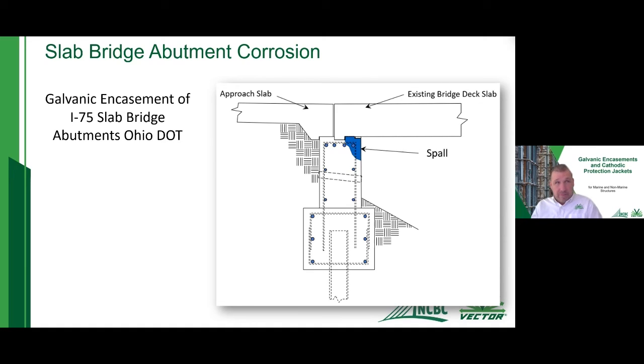So it's going to use very, very similar anodes that were used in these jacket encasements or these CP jackets. So you can think of this as just a very, very large atmospheric jacket that's going to be used in an area where it's a non-marine environment. So this is actually an abutment for the Ohio DOT. And so traditionally what they would do is they get some spalling that would happen up here. So you have your approach slab, you have your existing bridge deck, you have an expansion joint above it. That expansion joint fails all the time, so you get a lot of de-icing salts and chlorides that are coming down onto that abutment wall, and you end up getting corrosion occurring.